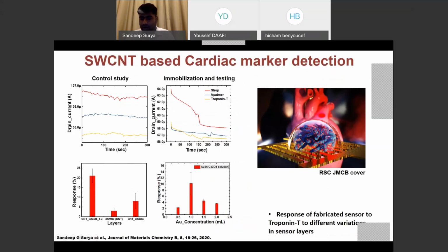Once we have prepared the device, we immobilize the surface. This control study corresponds to single wall carbon nanotubes alone and the detection process. Here, what I have shown you is the corresponding response of the signal with respect to gold loaded cobalt oxide nanorods on top of single wall carbon nanotubes. So the figure that I've shown you here can give a better analogy.